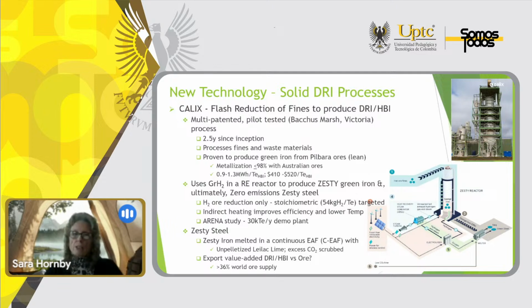And they feel that they can do it with 1.3 megawatt hours per ton of HBI, and the cost would be a maximum of $520, and that's Australian dollars. So that would be 470-ish US dollars. It uses green hydrogen, but it's only in contact with the ore, not as a fuel. And they can produce from this zesty green iron a zesty steel, and the diagram is shown at the bottom. So they're going to take the hydrogen ore reduction, reduced iron, and they will put it to a continuous electric furnace with unpelletized Leilac Lime, which they also process, and they will scrub the excess CO2.